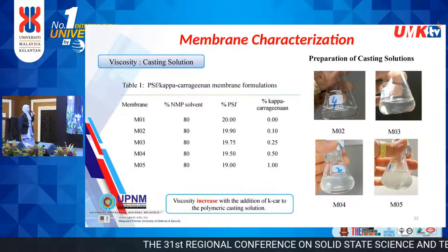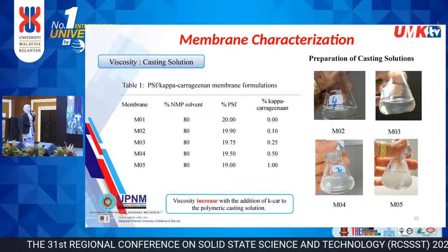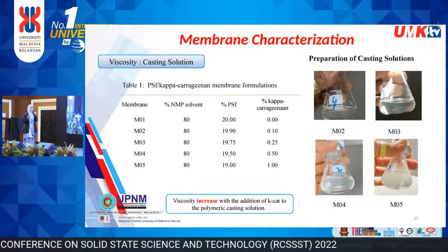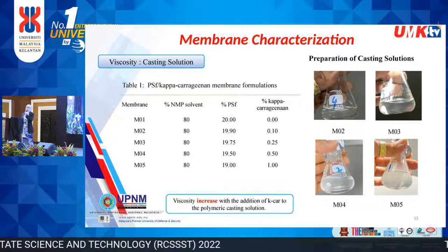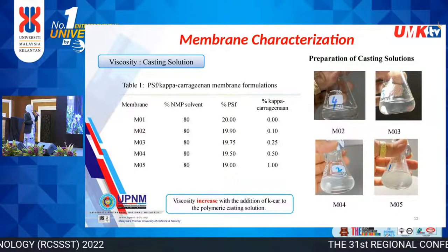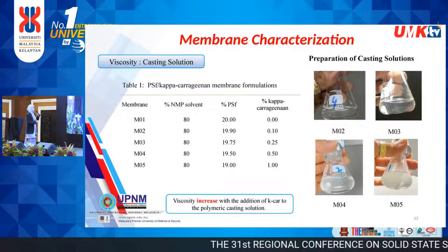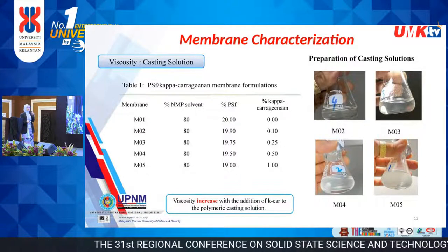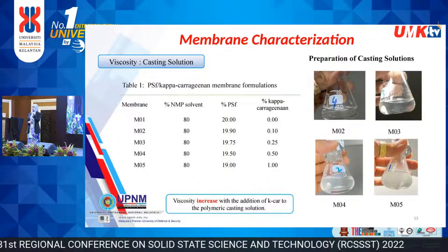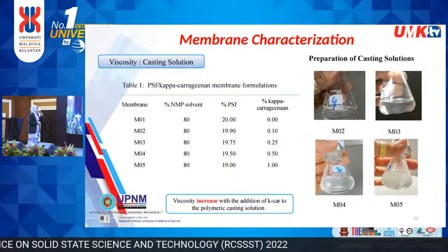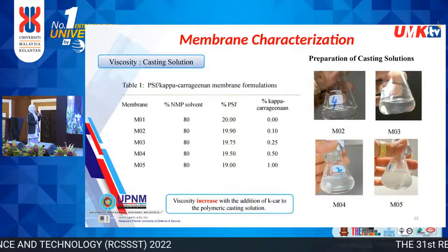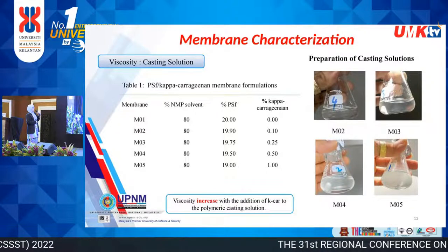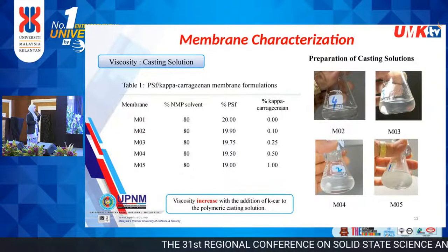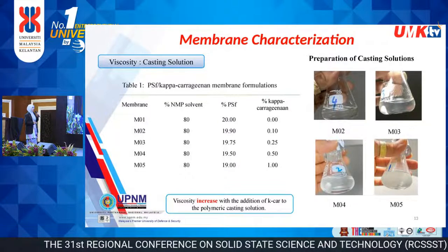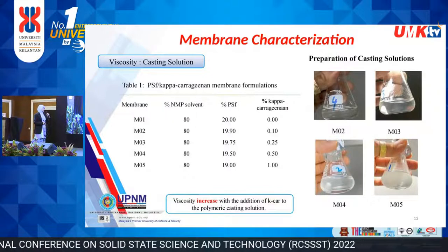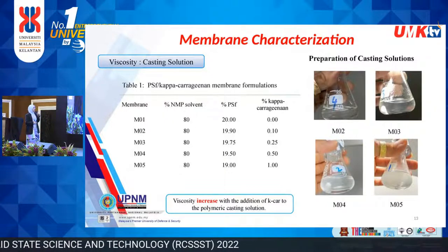Okay, so in terms of our findings, this is more to the preliminary work. We have a few samples here, membrane M01 to M05. M01 is the pure polysulfone membrane, whereby we don't add any carrageenan, and the rest are membrane formulations. Basically, what we can see here is that the viscosity of the casting solution for sure increased with the addition of kappa carrageenan to the polymeric casting solution.